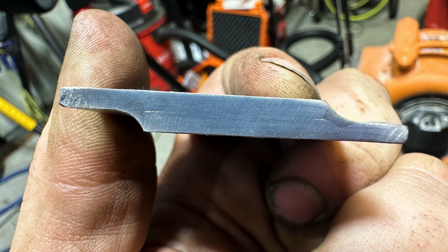The concave bead isn't really a huge issue, I guess. It's a little bit thin in the throat depth, but it's not bad, but acceptable. But the penetration and overall look of that cut and etch is way better on the left, focusing that heat on the root versus the one on the right.